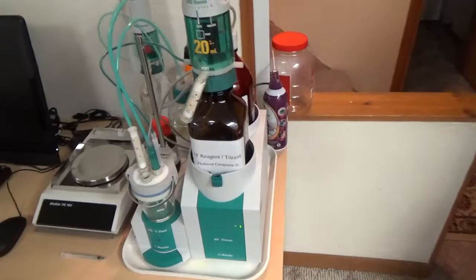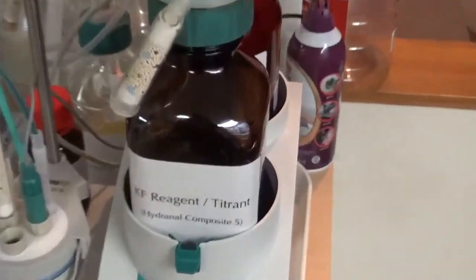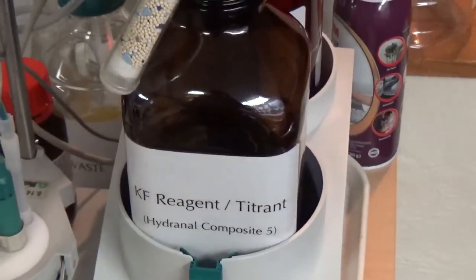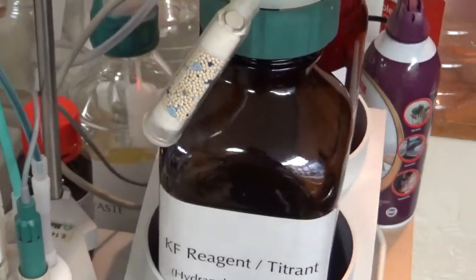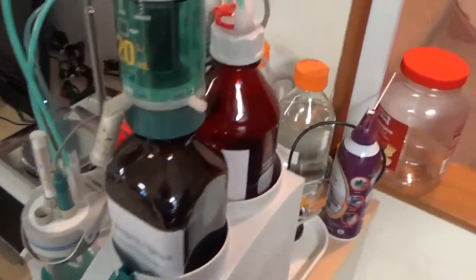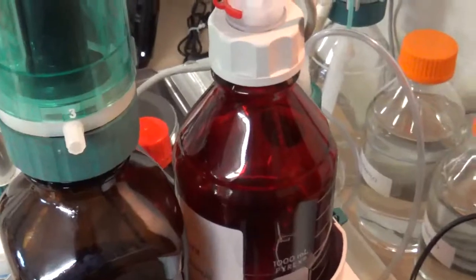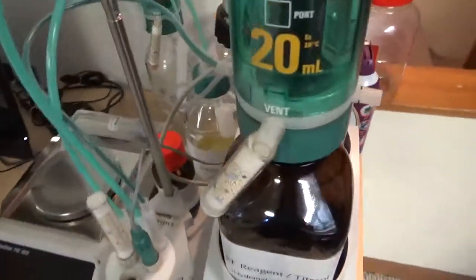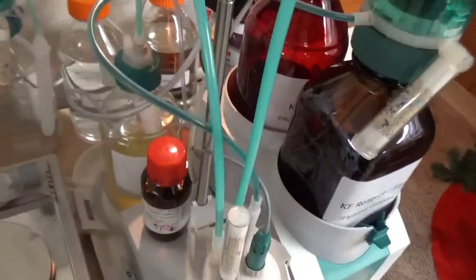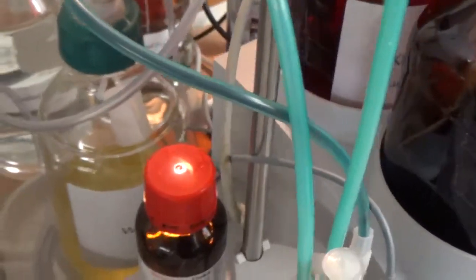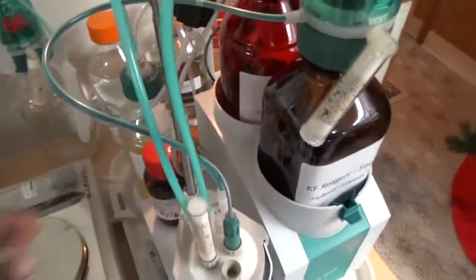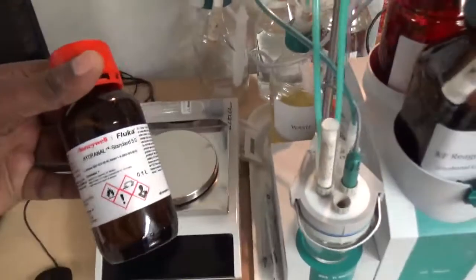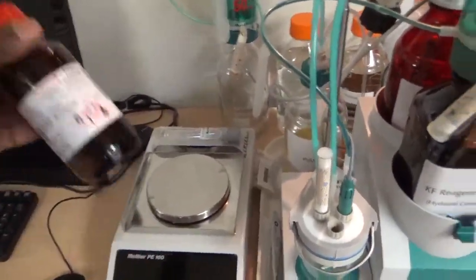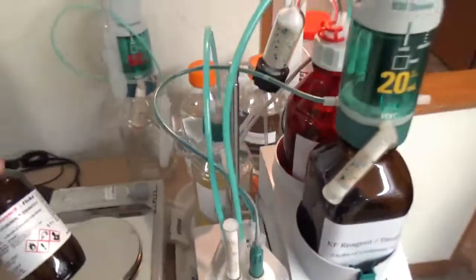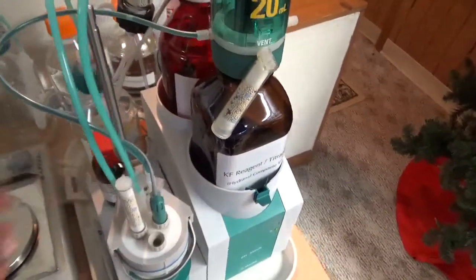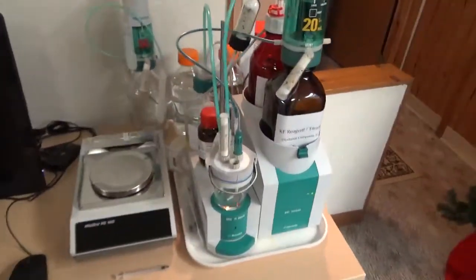We use Hydranal Composite 5 as the titrant, the Karl Fischer reagent, and since we are doing ethanol substitution for concrete moisture content, we use ethanol as a solvent. We also have a waste container for material after titration, and we use a water standard with 5 ppm water. We run the standard first to do the calibration of the Karl Fischer equipment, and then we do the titration.